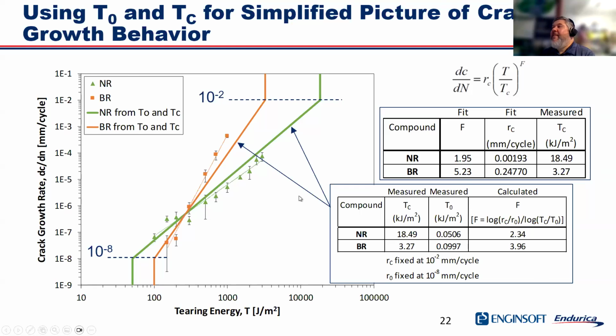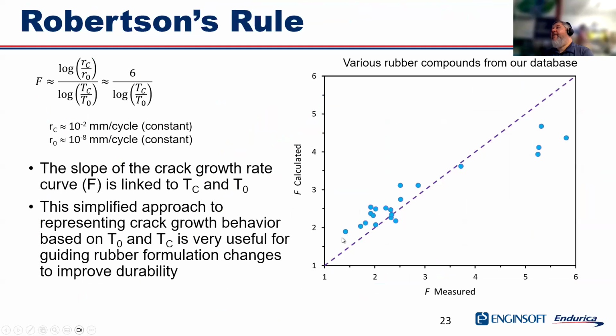And we've actually tested this out on a large data set. We've gone back to a database of materials that we've measured, both T naught and the crack growth curve, and we compared the actual slope values with the F values that we calculate using this simple method. And it's not perfect. You can see there's a bit of scatter here, but the correlation is something like R squared equals 0.8. Which, again, for purposes of doing materials development is probably good enough.